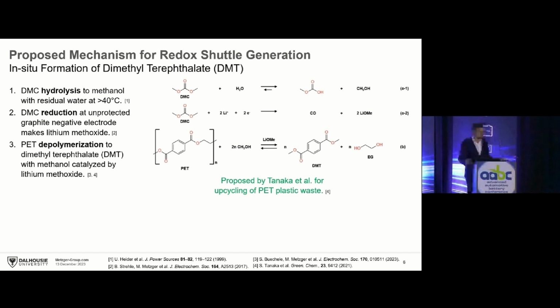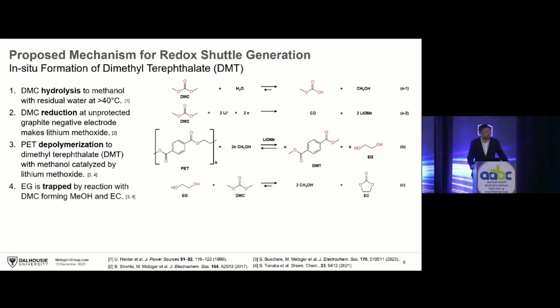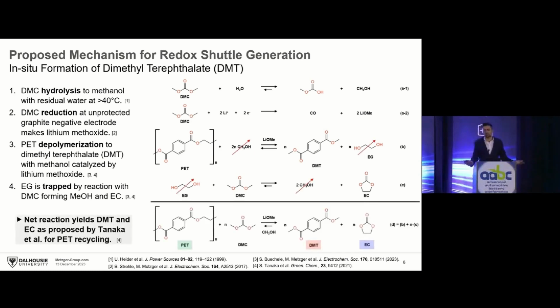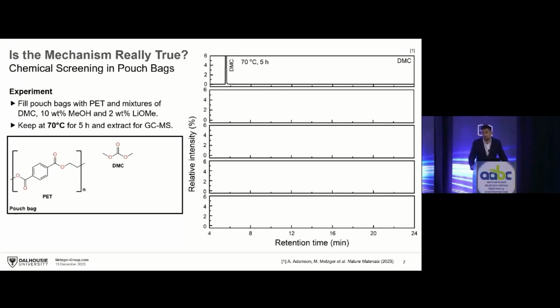So we were very intrigued by this reaction because we have all those ingredients, but we didn't find ethylene glycol. And that's because ethylene glycol can react with DMC to form more methanol, and it would also form ethylene carbonate, which is the molecule that we were also detecting in our gas chromatography experiments. And then you could form a sum reaction where you basically have PET with DMC and catalytic quantities of lithium methoxide and methanol to give you the DMT redox shuttle we were finding and also the ethylene carbonate we were finding. So we thought that this reaction really would make sense to explain the species we detect in our battery cells. But of course you have to convince yourself that it's really true, right?